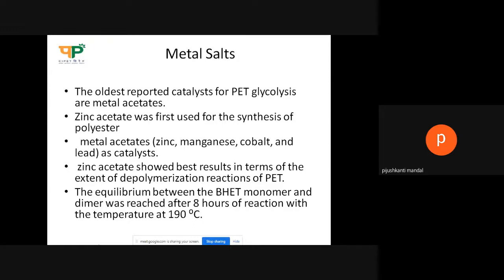The oldest reported catalyst is the metal salt. Zinc acetate was the first used catalyst for the synthesis of the polyester. Metal acetates such as zinc, manganese, cobalt, and lead are used as a catalyst. Zinc acetate showed the best result in terms of the extent of the depolymerization reaction of the PET. The equilibrium between the BHET monomer and dimer is also reached after 8 hours of reaction at the temperature 190 degrees centigrade, with the high percentage conversion of the BHET monomer